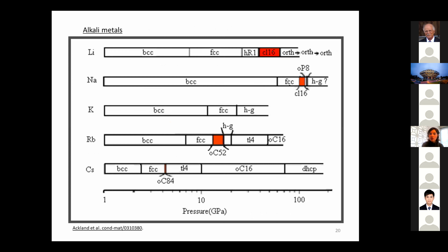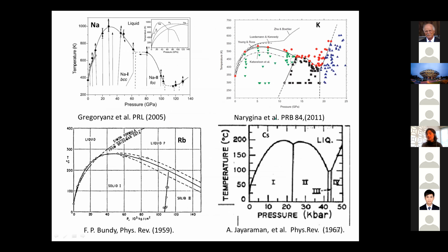Now, as a function of pressure, things are even more drastic. You stay at constant temperature and you pressurize these. All of them go through this sequence of phase transitions. Initially, they go to more packing, but eventually the electronic effects become so dominant that they go to exceedingly low symmetry phases that are very, very counterintuitive. As a consequence, if you want to see quantum melting, a maximum in the melting curve as a signature of quantum melting, good luck, because this is the melting temperature of all of these things. And because they go to the lower symmetry phases, they get their maximum.